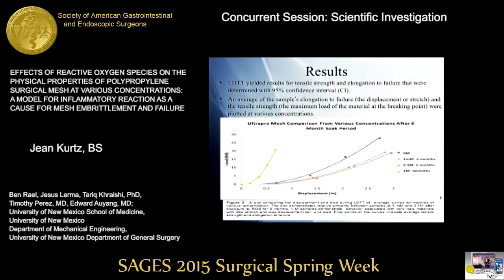So our results were all determined with 95% confidence interval. The graph you see before you is the average of the different concentrations. What you see on the x-axis is the displacement, or the elongation, and what you see on the y-axis is the load. So what you can observe if you look at the blue line, that's the regular fresh out of package mesh samples. You'll see that they're quite strong.